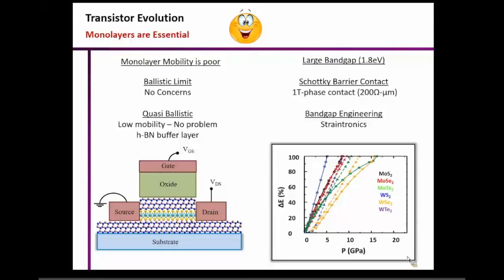And these materials actually have higher effective mass, which allows you to drive more current compared to silicon. And if you're not working in the ballistic limit for other kinds of devices, you are in the quasi-ballistic limit. There I have some strategies to improve the mobility, because I can sandwich a layer of MoS2 between 2 hBN layers, and I can enhance the mobility by several factors. So that can help me boost my mobility number. The other concern that generally appears with monolayer 2D materials is that the band gaps are a little bit too high for a semiconductor, because silicon has 1.12 eV and monolayer MoS2 is 1.8 eV.